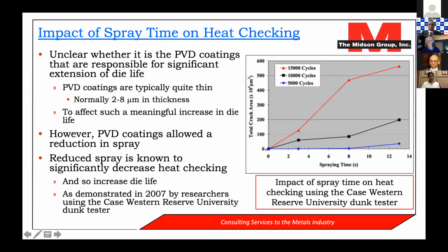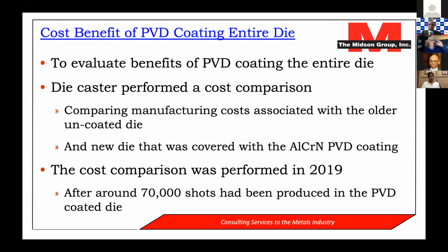And if we go to no spray time, at least in the test they did at Case Western, they saw no heat checking at all. Not to say that we wouldn't in a real die, but that's what they saw. So clearly reducing spraying allows us to minimize heat checking. And so I personally think that the use of the PVD coating allowed us to reduce spraying, allowed us to get an increase in die life. But that's not yet been proven. That's just kind of my opinion at the moment.